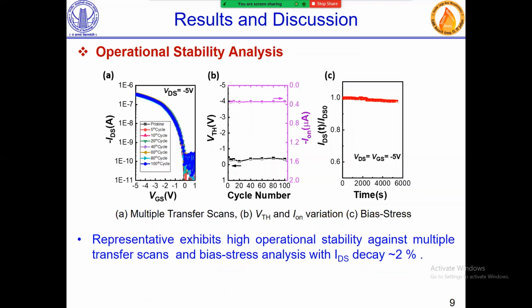Operational stability analysis. In this, multiple scans of the transfer characteristic up to 100 cycles were conducted, and it is seen that there is an overlapping in the transfer characteristic. Figure B is extracted from figure A, in which it shows that threshold voltage shows minimal variation and Ion also shows minimal variation. Figure C: on applying bias stress to a device for up to 5400 seconds, there is a 2% decay in the current, which shows that this device is highly operationally stable.